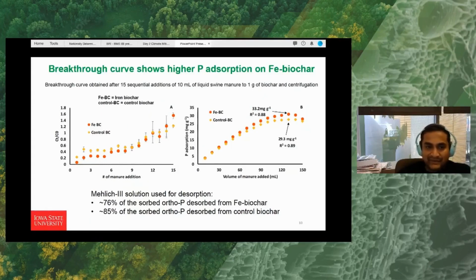phosphorus absorption. The left hand side is the plot of Ct/C0 versus number of manure additions, and on the right hand side is the phosphorus absorption versus volume of manure added. So the blue is the control biochar and the red is the iron biochar. On the right hand side, you can see the absorption capacity is around 33 milligram per gram of phosphorus using iron biochar, whereas control biochar is also showing around 29 milligram per gram.